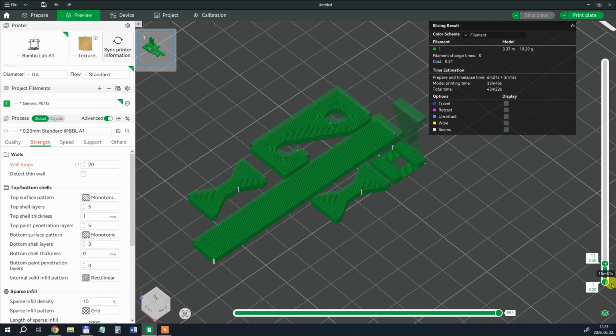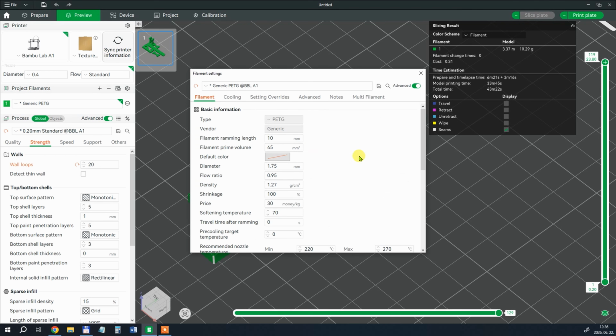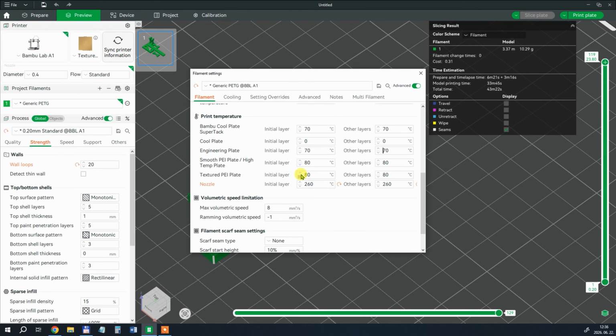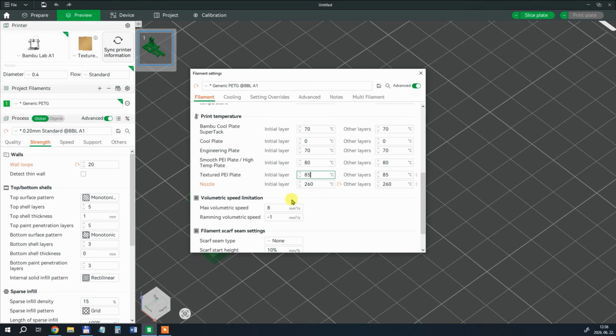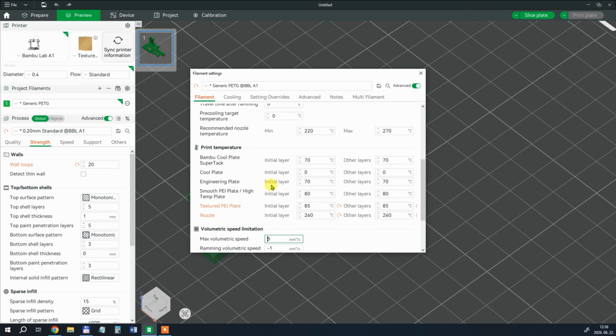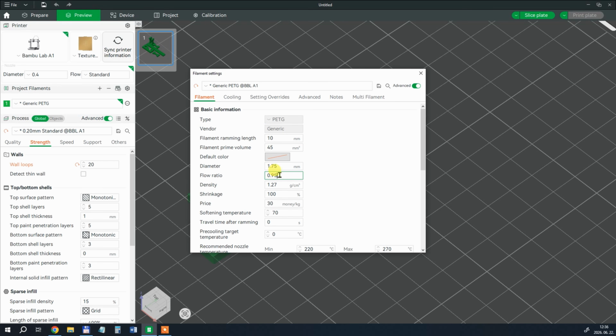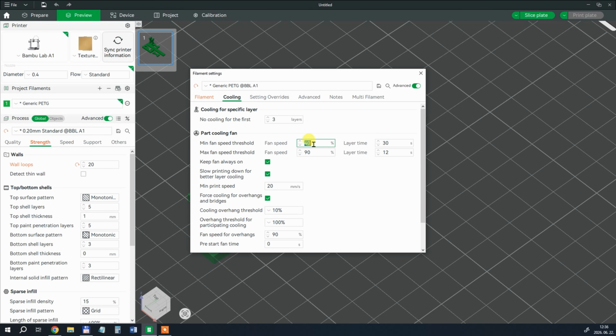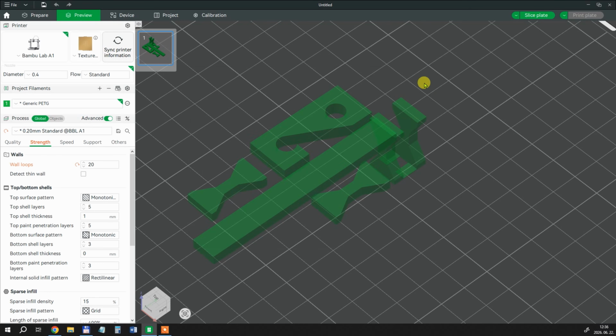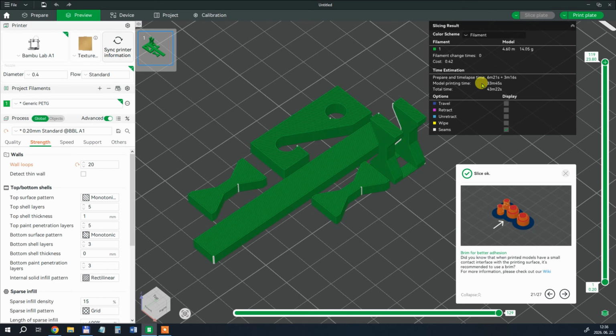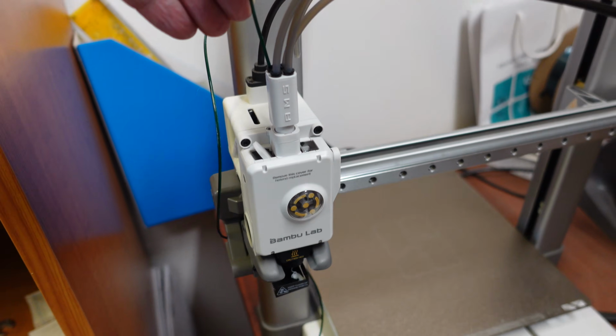All test objects are solid inside, printed with the maximum number of walls. Generic PETG is the starting profile, but of course it's modified. 260 is the nozzle temperature, 85 the bed on the textured PEI, 8 the maximal flow, and of course very important is 1.3 the flow ratio, that's the extrusion multiplier, and I'm reducing the retraction length between 30 and 50%. And with this I will need almost 5 meters of filament.